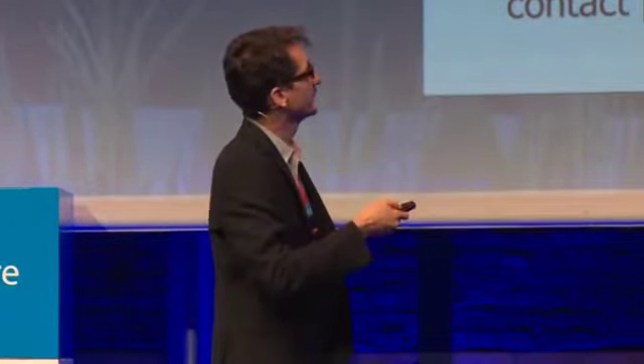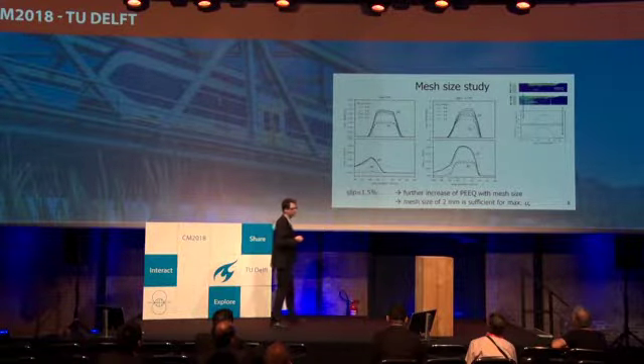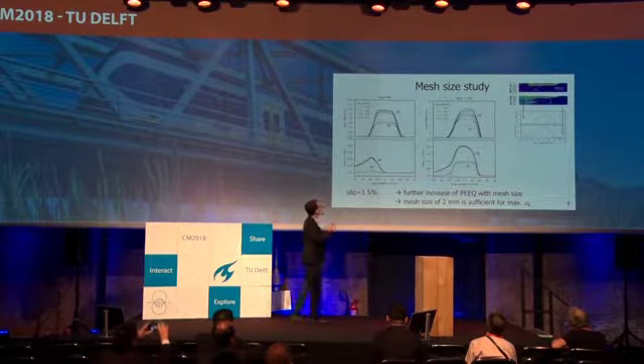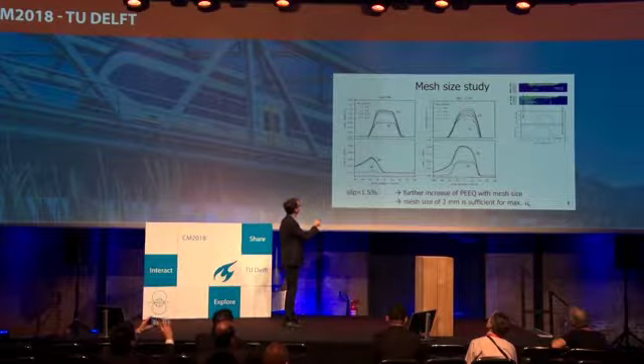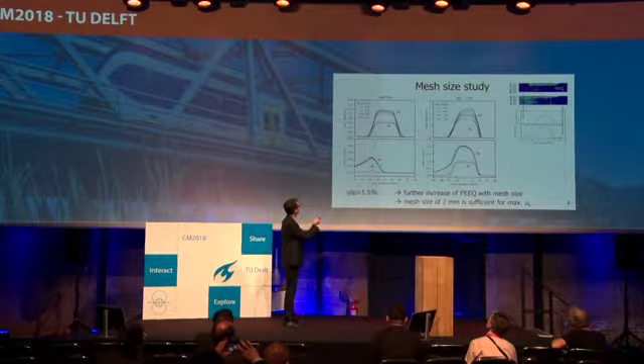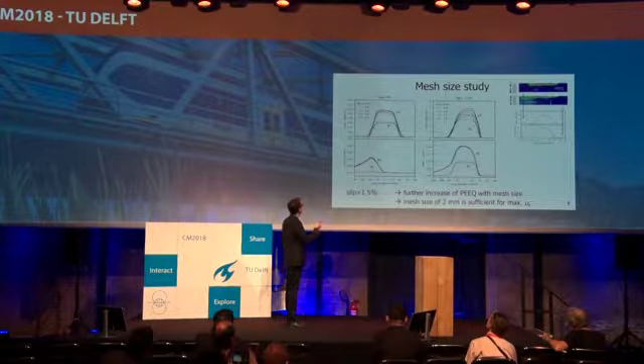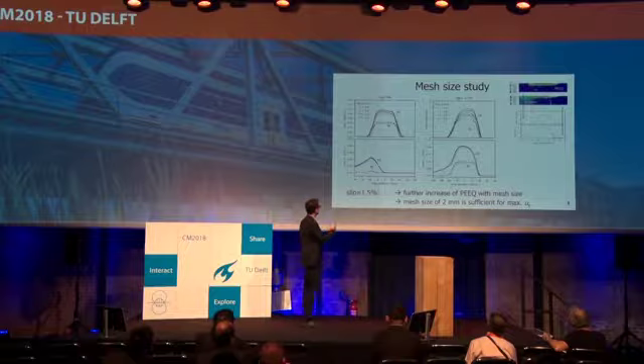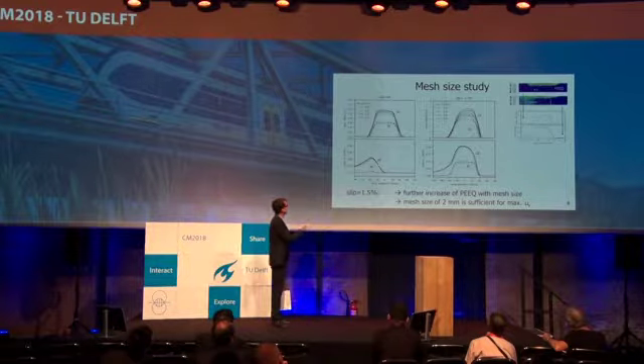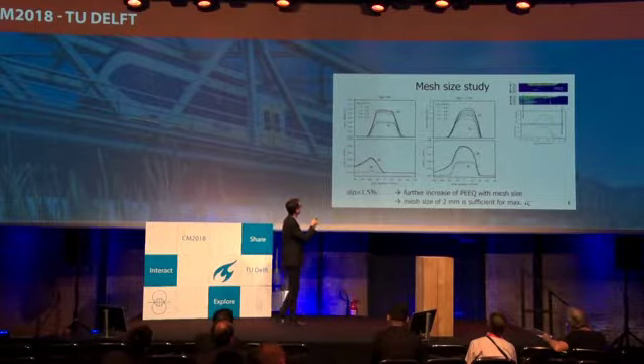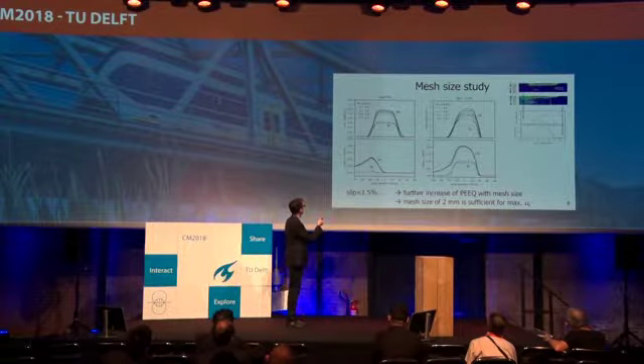What we also see here is the mesh dependency, and we see we get quite good and accurate contact patches if we already use 1 or 2 millimeters of mesh size. That's sufficient for that application. Now looking at those different mesh sizes and a certain rolling length, in this case it's 60 millimeters, we can look with a slip of 0% how uniform our plastic deformations are. In that case, they're quite uniform. And our shear displacements, in that case, they're not uniform at all because we don't have any real slip and it's just an effect on the border. But we also see that the mesh size is not that much influencing that.